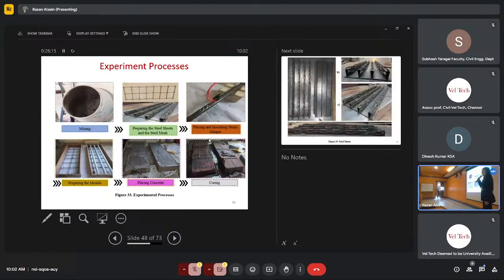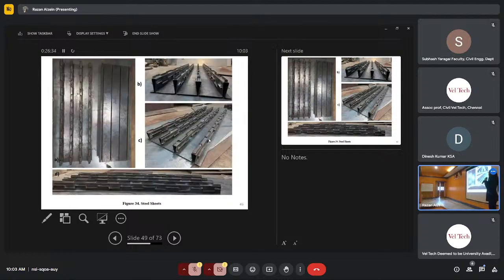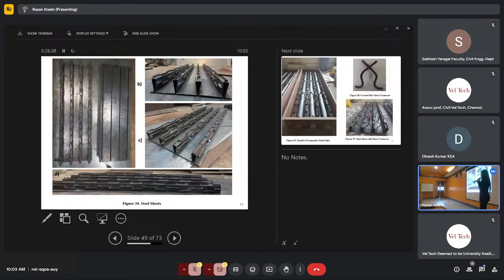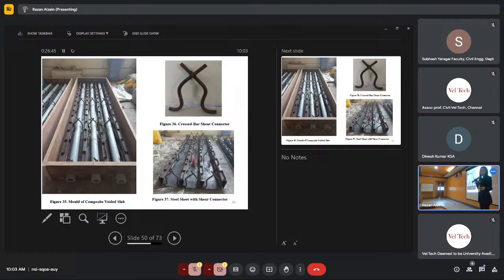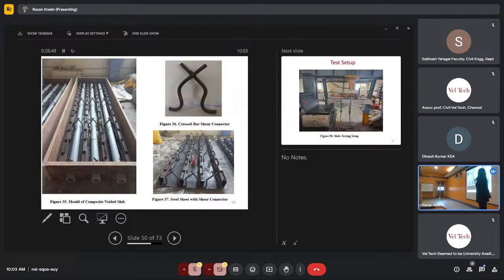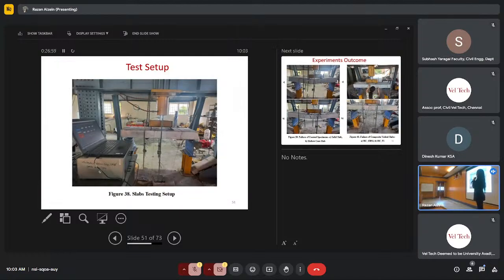Regarding the experimental investigation, I will clarify the process starting from the mixing, preparing the slabs that were particularly prepared for us, and installing the strain gauges, the molds that were designed and made specially for our study, placing concrete and then curing them for 28 days. Here are the sections of the slabs to illustrate how they look, exactly like the modeling. Here is the mold that was designed particularly for this purpose. Here is the shear connector, the crossed bar shear connector, and here is the welding process to the slab. Here is the setup that was done in the structure lab in our college building.